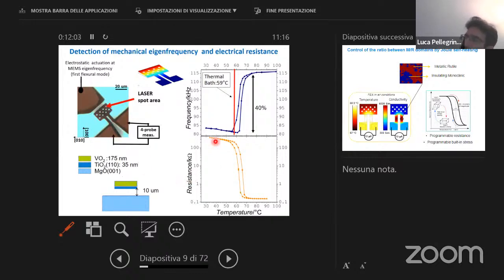What we did was to measure the resistance as a function of temperature. Here you can see the resistive transition, on a logarithmic scale. At the same time, you can see the change of the oscillation frequency, because we also make this cantilever oscillate by a laser, and by electrostatic actuation we can detect this microstructure. So meanwhile we measure the resistance and the resonance frequency, the eigenfrequency, and we see that at the transition we also have a change of resonance frequency.